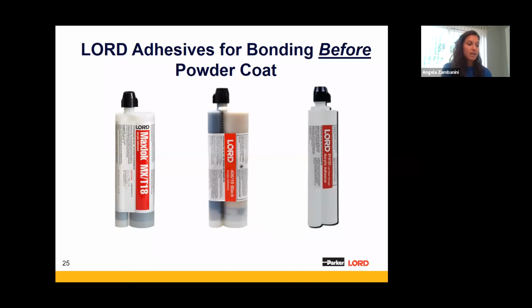So Maxlok is our top performing adhesive for powder coat just because of its superior temperature resistance and tensile strength relative to our other acrylics. You will want to use this adhesive if you do have really, really large or really heavy parts, or if you're using steel and you're using metals such as especially galvanneal or galvanized, as it gets really, really good performance on those.